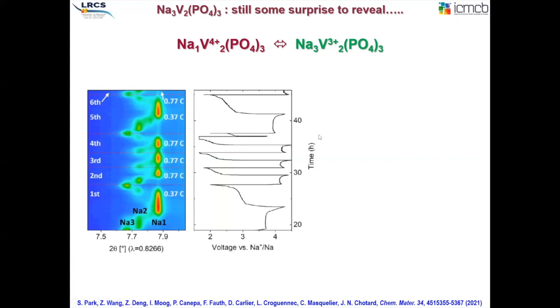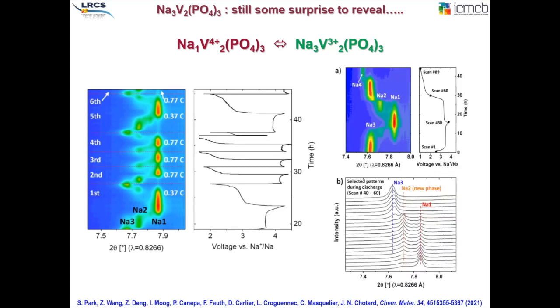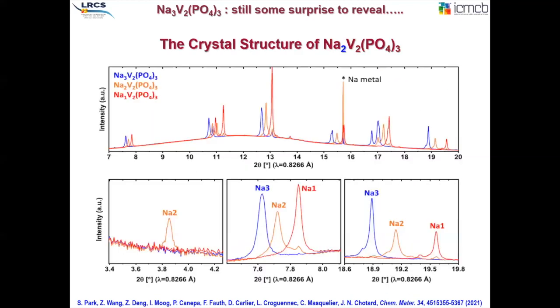And then we undertook many other studies upon cycling at different rates and for extensive cycling, up to the sixth cycle here, where we always saw the existence of this intermediate phase between Na3 and Na1. And definitely it is there. By carefully monitoring our electrochemistry, we could indeed isolate this phase, where you can see here the diffraction peaks of this Na2 phase, which had never been fully observed and determined before, occurring in between the Na3 pristine one and the Na1 pristine